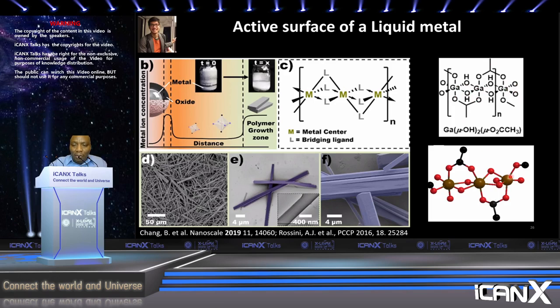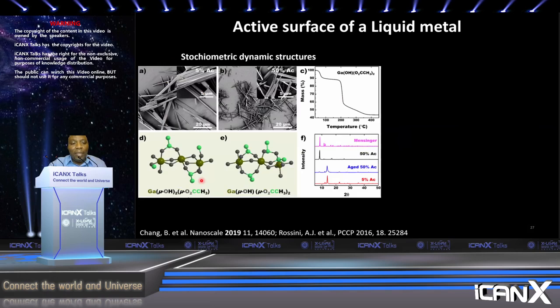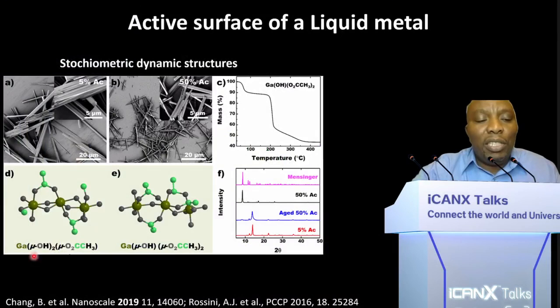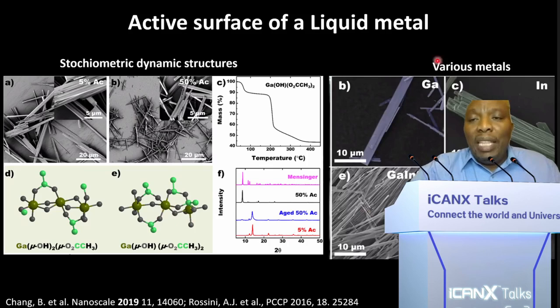Although it had a little twist, it does not inhibit self-assembly, as you can see in these structures here. And you can even see this is a huge quantity of material that we made. We can also tune the stoichiometry and end up with different kinds of structures where we have more water and less acetate. But those structures end up relaxing back to the acetate with one water or one OH from the water interloping across the metal centers. We can also make these from other metals.